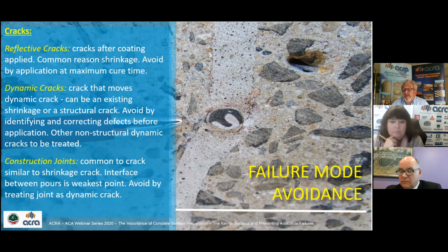Dynamic cracks. A crack that moves is dynamic. A crack can be an existing shrinkage crack or a structural crack. The difference is that a shrinkage crack usually moves in two directions in the same plane. Structural cracks move in multiple directions in multiple planes. This can be avoided by identifying and correcting any defects before application, treating dynamic cracks by bridging, injection bonding, routing out and sealing with a compatible sealant.